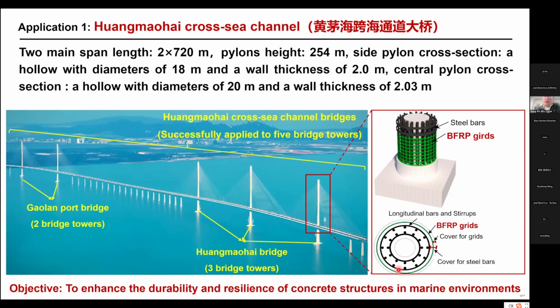So the FRP grid is placed in this concrete cover. The concrete cover is over 8 centimeters, very thick. But if we use steel grids, steel grids cannot be placed at the very outside. They still need 4 to 5 centimeters of cover, so they cannot control the cracking well. If we use stainless steel, although in the early stage it can control cracking, finally, because of the differences in electrical potential, the stainless steel will accelerate the corrosion of the inner steel. So it's still not a good solution considering durability.